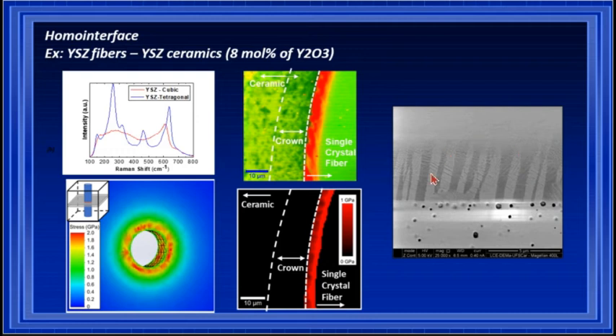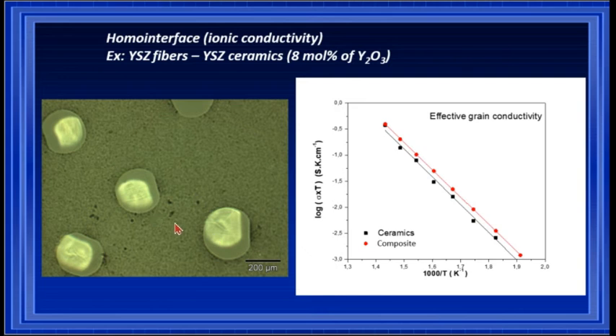Here we show a micrograph of this region, where we can see the phase transition from cubic to tetragonal in these composites. And when we measure the overall conductivity of the sample compared to the ceramics without fibers, we can see that we have an increase in conductivity regarding the effective grain conductivity when we analyze the fibers. The fibers within the ceramics give us an increase in conductivity compared to the ceramics itself.